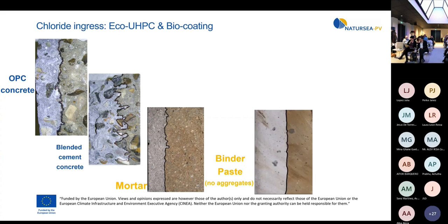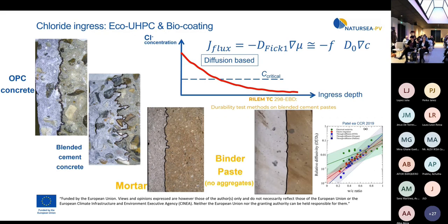But now we don't have the big aggregates, but still we have the transition zones. So this is how it would look for the mortar, but it's not UHPC, it's just normal mortar. And here you can see it for the paste, so just the binder. We can model it by the diffusion model. This is just a simplified way. But the diffusion coefficient is one of the key performance indicators, because it will show how long the chlorides take to reach the reinforcement steel.